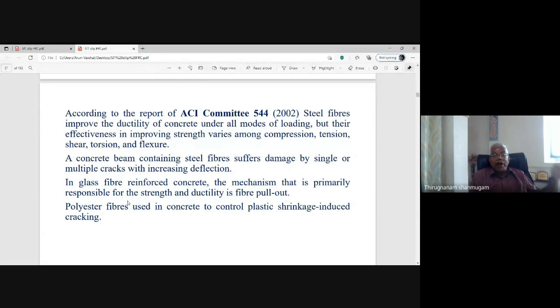plaster. If you apply the cement plaster over the surface of the wall, you cannot notice the shrinkage cracks in the plaster. Otherwise, the shrinkage cracks compulsorily appear because of the evaporation of the water or setting action of the cement paste. So in commercial practice also, these polyester fibers are used. 125 grams per bag of cement is normally adopted.